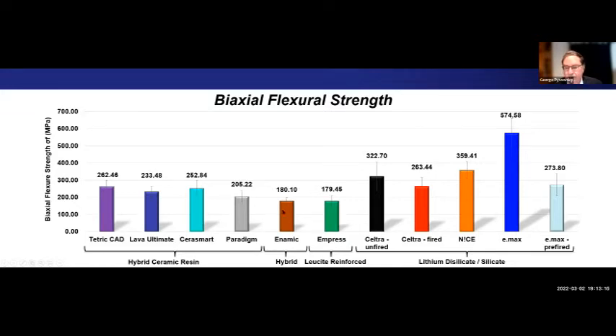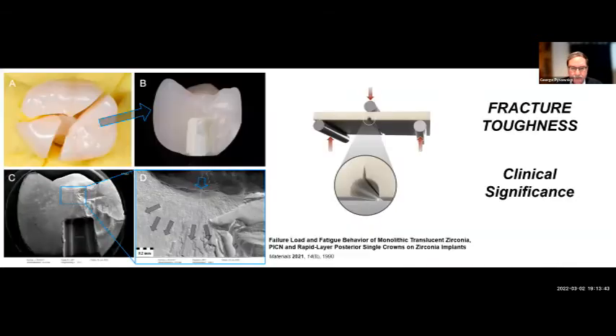Enamic, which is a ceramic structure infiltrated with resin, about 180. Empress, a leucite reinforced material, about 180 also. And then we get to the lithium disilicate materials in a range from the 250s to mid 300s all the way up to 570 for Emax as a reinforced ceramic material. These were very exciting developments because the reinforcement of crystal structure increased the strength of these types of materials.